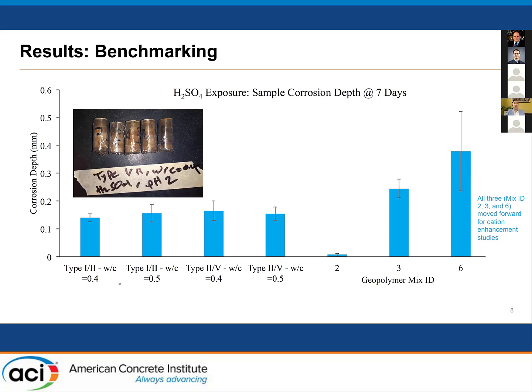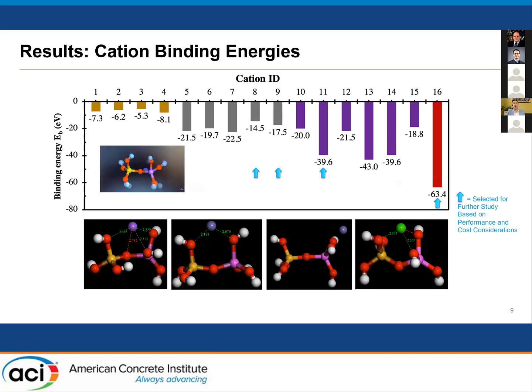And so we wanted to know, really from a fundamental thermodynamic perspective, which cations are the best at stabilizing the geopolymer framework. So Claire White's group did a really terrific job at running molecular dynamics simulations to calculate the binding energies of different stabilizing cations inside of the cement paste that would charge balance the Si-O-Al bond.